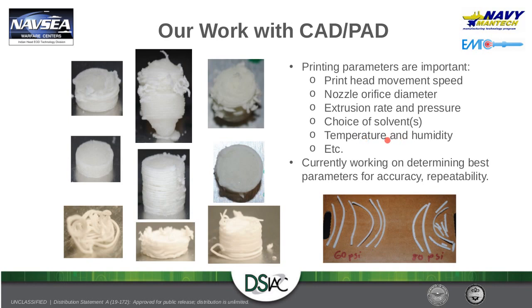Temperature and humidity are two very interesting parameters that we saw because of the volatile solvent that we're using. If the ambient temperature was too high, that would cause the solvent to evaporate too quickly, causing the material to simply dry out and even potentially cause a nozzle clog. And if the ambient temperature was too low, the material would be way too slow to evaporate. So as we're printing, the rate of evaporation wouldn't be high enough, so we would actually be left with a very mushy print with very little body.